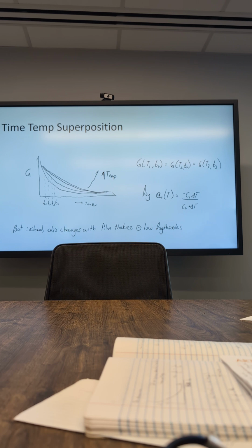So in the last but one sentence, they say that additionally, changes in the modulus of the PMMA thin films do not directly correlate to the thin film Tg. This result raises questions about the applicability of fundamental concepts such as the WLF equation that relate Tg to other physical properties. So they are trying to say that as we go to these nanometer scale thicknesses, you may not necessarily be able to use this WLF equation to see the effects that occur in that system.